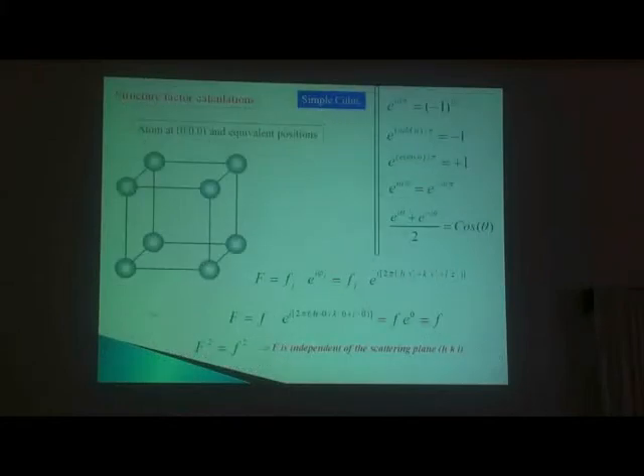For a primitive unit cell, how do you calculate? In a primitive unit cell, though there are 8 corners, each corner is shared by 8 adjacent unit cells. Ultimately, the contribution to this unit cell is only 1. Take this as the origin. So what is the structure factor equation? Only one atom, put it as j, and then put x, y, z as 0, you get 1. So it is the atomic scattering factor. What does it tell you? It is independent of the scattering plane. Any plane, you have the same intensity.